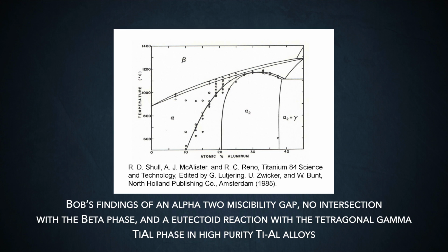And in addition, even at higher temperatures and aluminum contents, we showed that there was a eutectoid reaction between the alpha 2 phase and an even higher aluminum content single phase called the gamma phase, which is also a very important, industrially important structure, because it goes to very high temperatures before it decomposes into some other multi-phase system. So that was basically what I did, and it was very, very good to have finally clarified that, since it has a profound impact on industrial alloys.